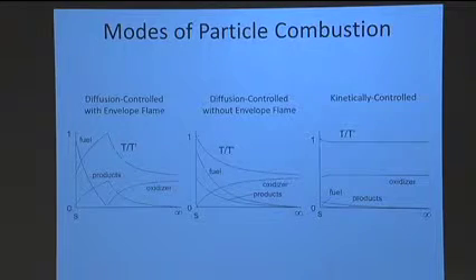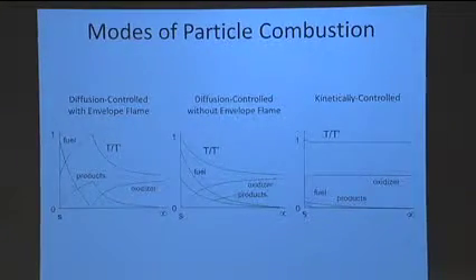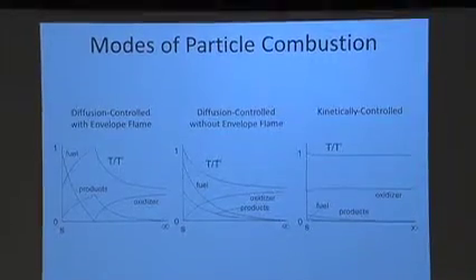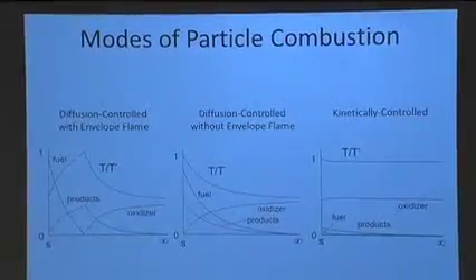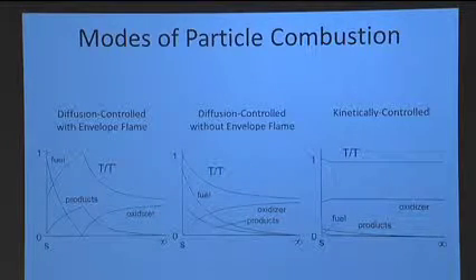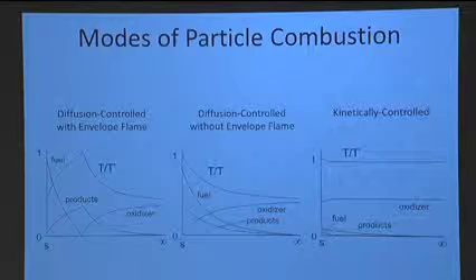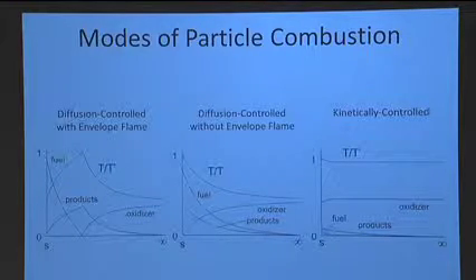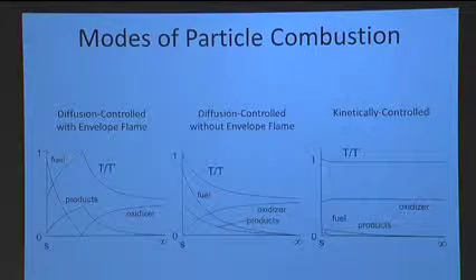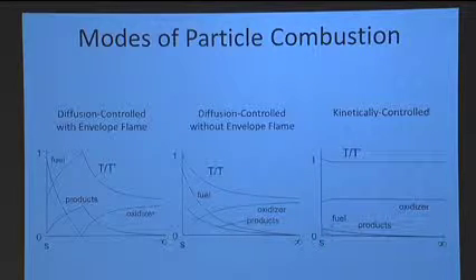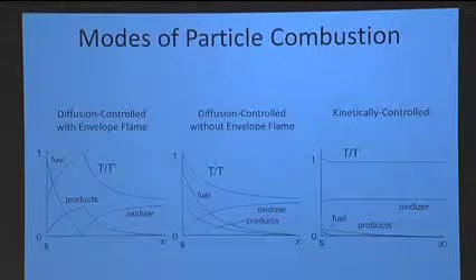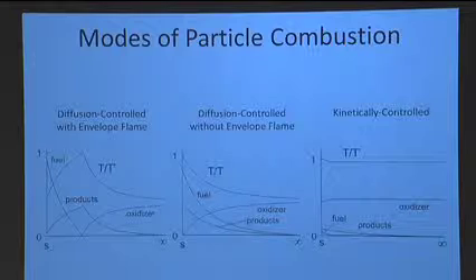Okay, now I've been talking thermodynamics. When we start talking about particles themselves, we introduce a length scale into the problem. And if I introduce a length scale, I'm essentially introducing a time scale for mass and energy transport. And again, just looking at simple concepts here, what can one learn as to how these materials might start behaving as I start going from a large length scale down to a very small length scale? Well, typically, if I look at this from two extreme limits, one can look at a situation where I have very, very fast transport of mass and energy, and what's limiting the process then is really the chemistry.